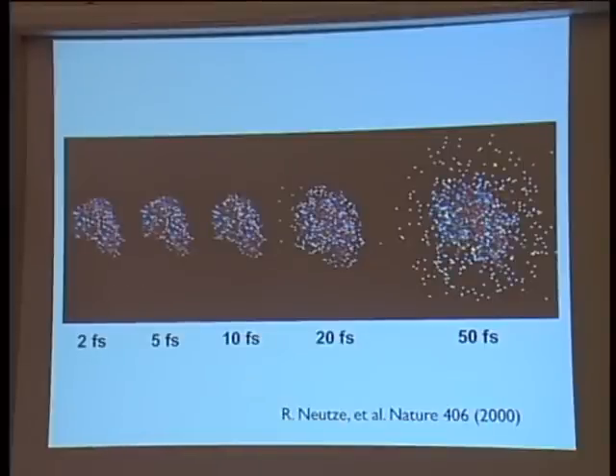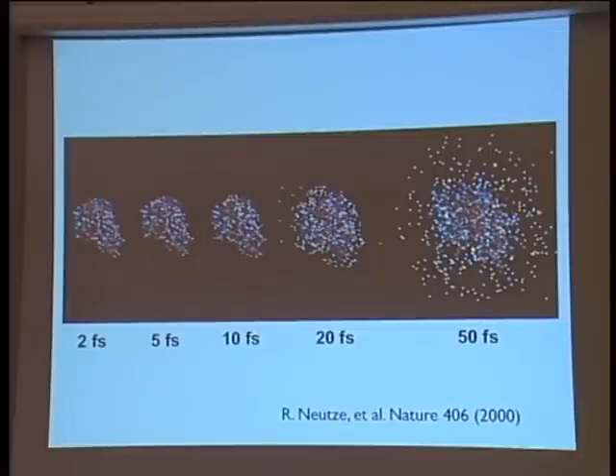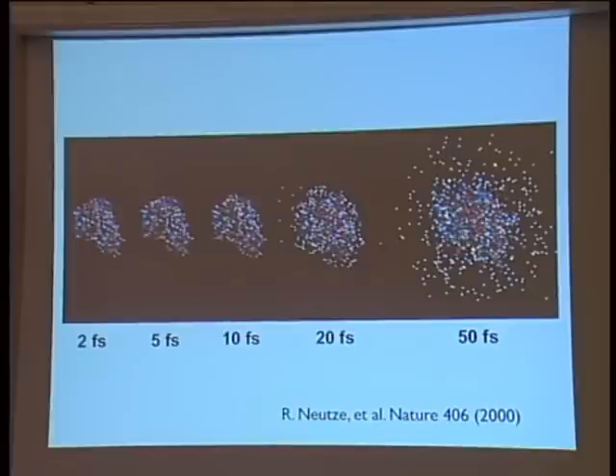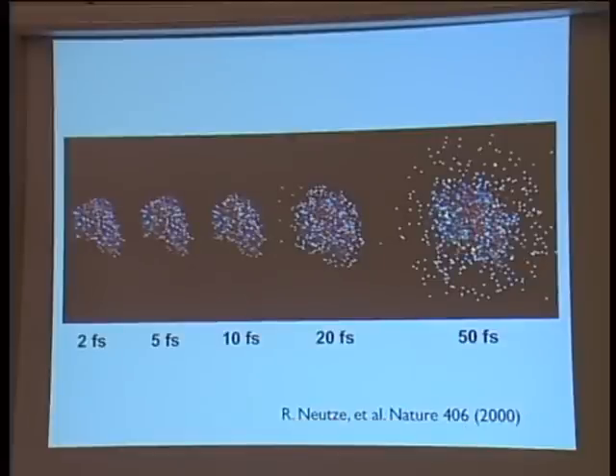These are simulations. We see that it takes a while before atoms start moving, and even atoms that are very small actually have inertia. So it takes some time before they start moving and explode, basically, at the end. So we have this time window of about 10 femtoseconds where the molecule is still as it was originally, pretty much intact, not damaged, so to say.